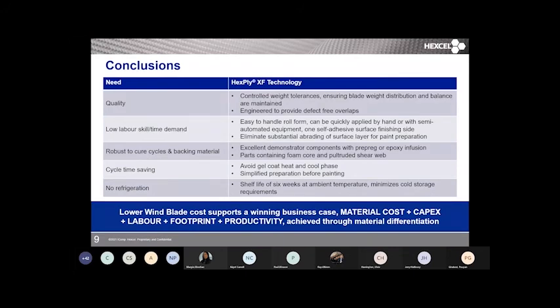The material has to be very robust, and we've produced demonstrated components with pre-preg or with infusion, epoxy infusion backing, and the full range of high and low vacuum pressures that you might anticipate you would see. And also, there were some great pictures in the presentation earlier. You saw all of the other materials that are in a wind blade. So there's foams, there's balsa, there's pultrusions, there's carbon spar caps. The demonstrators have been done, and the technology is tolerant to all of those as backing materials.